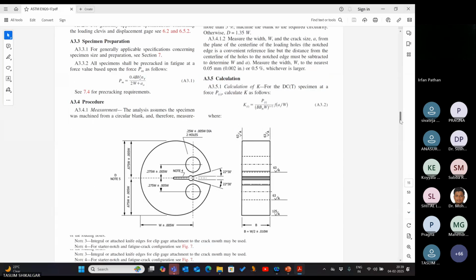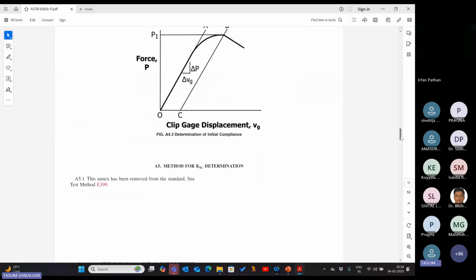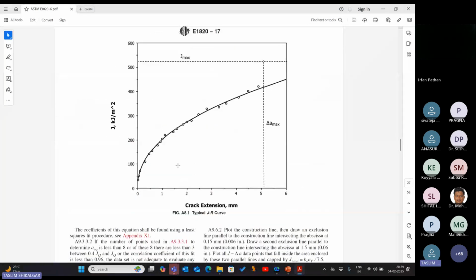I think the J-R curve is not available here, but this type of curve is available. They generate it with the help of the CT specimen: the J versus crack extension curve. And this is the fracture property. Sometimes people don't want these curves. People want the J initiation at zero crack extension. That is also a useful property. If the crack initiates, after that the crack is dangerous. So people want to know how much the J initiation is. Sometimes industry uses only one value: is it safe or unsafe for these specimens?